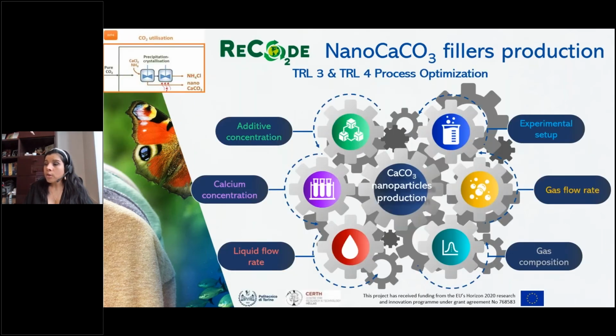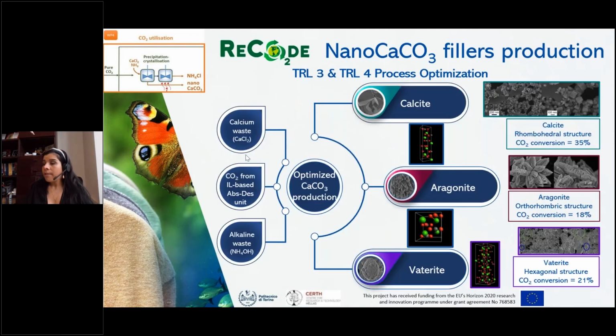Then, regarding the conversion of this CO2 in the first kind of technology, the calcium carbonate precipitation system, we also started from TRL 3 at Politecnico di Torino and CERTH, and we have optimized the process from different points of view regarding the additives concentration, the calcium concentration, the flow rate, so different operative parameters, in order to be able to control the different crystalline structures and the size of the structures that we obtain.